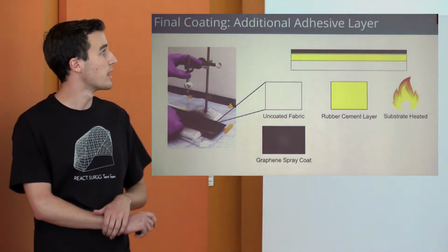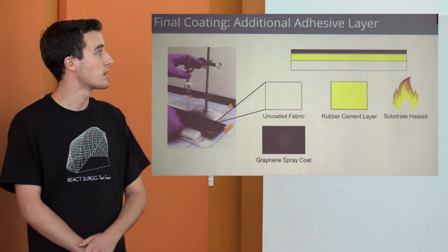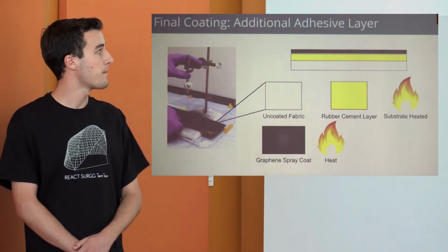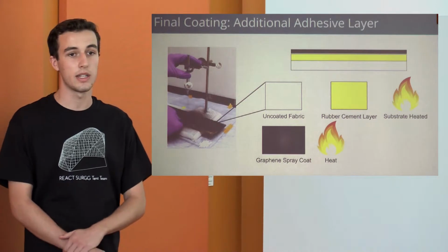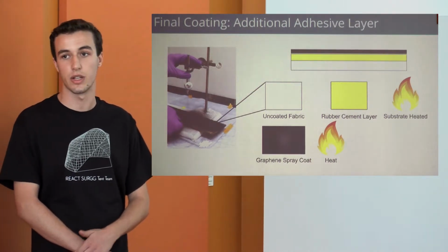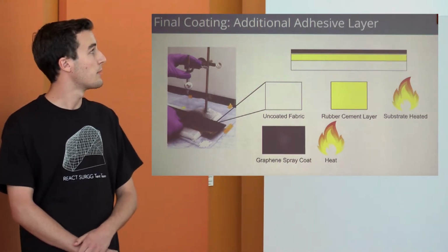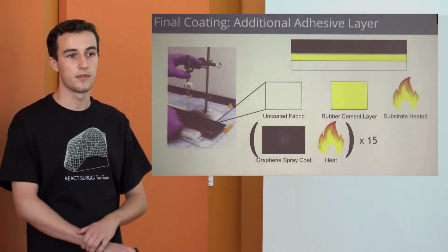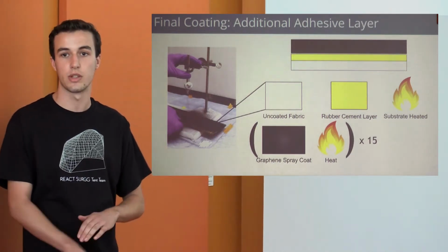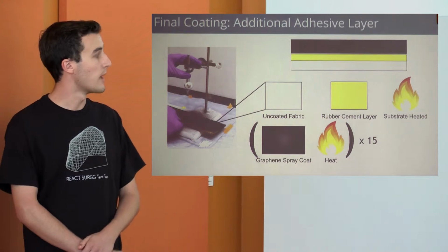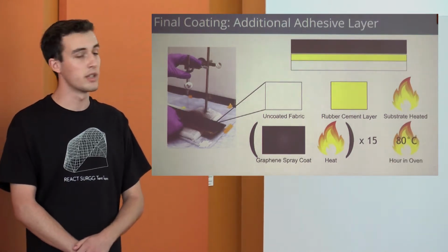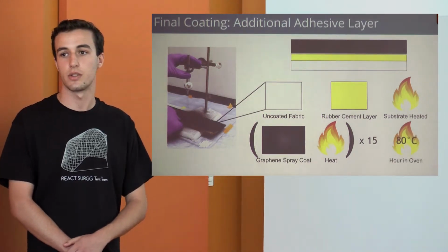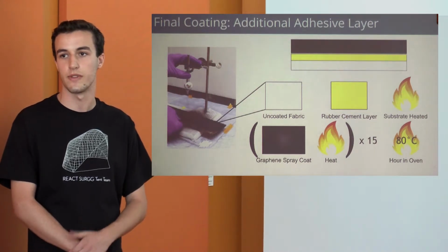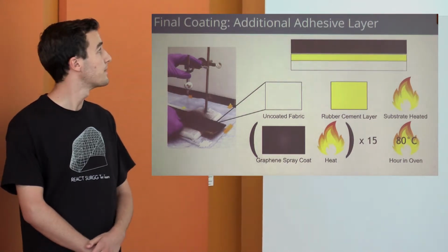That was just to get a nice even coat across the whole substrate, and then heated with a heat gun again to evaporate any of the water that was still on top. And that process was repeated 15 times to have a thick coat, to make sure the entire thing was coated. And then afterwards, it was put in an oven at 80 degrees Celsius for an hour to make sure that all of the water was evaporated and might have been missed by the heat gun.